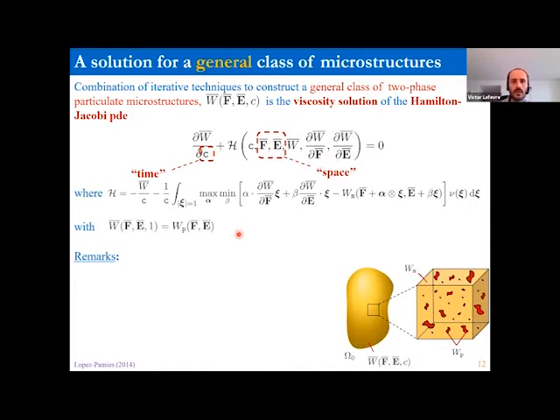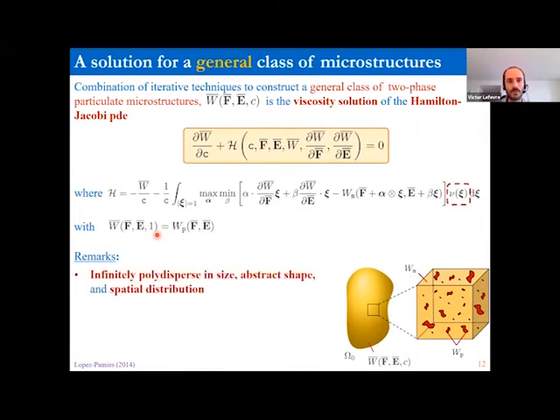And so the way to understand this initial condition is that you need to integrate in time, or in volume fraction, from the initial condition that's given at c equals 1, which corresponds to 100% volume fraction of particles. And so if you only have particles, obviously the behavior of the composite is the behavior of the particles. So you need to integrate in volume fraction from c equals 1 to any volume fraction of interest, say 0.15 for 15% volume fraction.